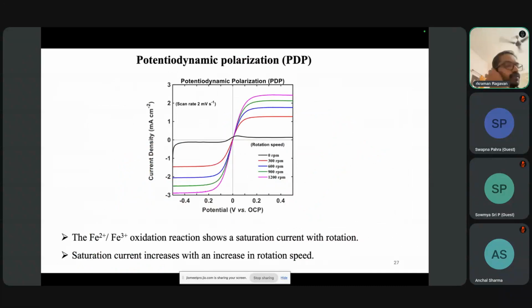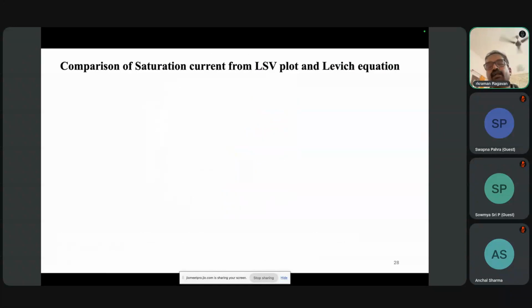You will see, this is a rotating disc electrode experiment. This black line is a CV, that means at 0 RPM. This peak is oxidation of ferro to ferri, and this peak is reduction of ferri to ferro. And when I start rotating at 300 RPM, you will see the current is increasing. This is called the limiting current. That's the maximum current possible for a given rotation, because the species only diffuses at that speed. Beyond that, it cannot diffuse.